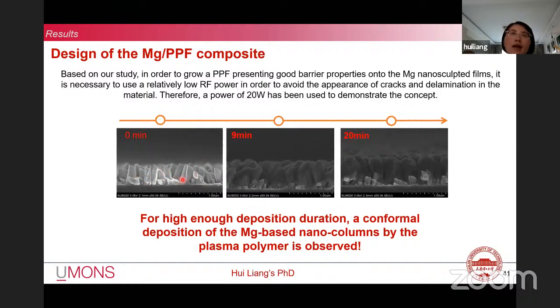When the deposition time increased to 9 minutes, the top of the magnesium column, along a length of about 200 nanometers, was covered by a CH layer, and the height of the column was observed to increase from 200 nanometers to 300 nanometers. When the deposition time is increased to 20 minutes, the whole nano column will be covered, and the thickness of the coating will gradually decrease from top to bottom. According to those stages, under our experimental conditions, it will take at least 10 minutes to obtain a reliable coating to protect Mg from oxidation. For a high enough deposition duration, conformal deposition of the Mg-based nanocolumns by the plasma polymer is observed.